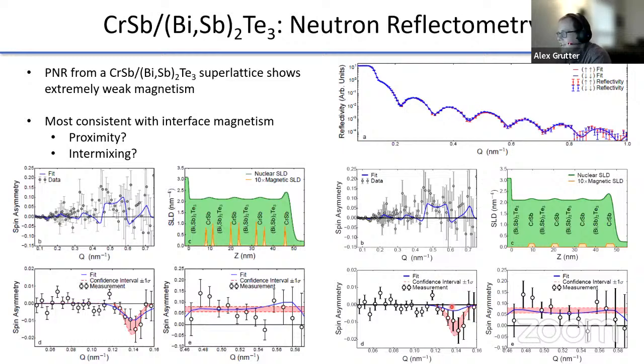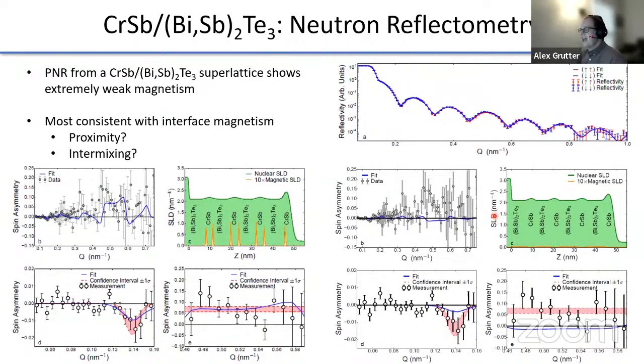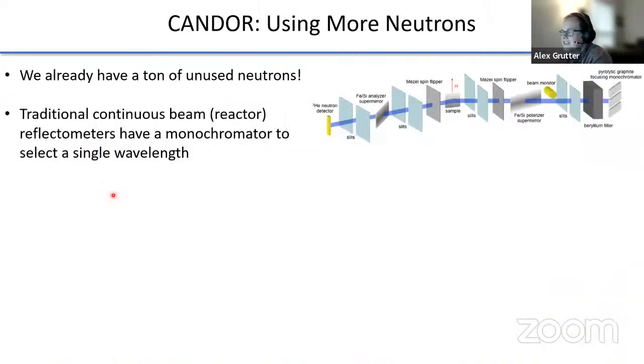It doesn't quite catch it here if it's magnetic chromium antimonide, but it's close. It definitely isn't uniform magnetization in the bismuth antimony telluride. But what this should really tell you is that after 5 days of counting on this, we got a very noisy data set. And so it worked, but barely. And clearly the problem that we often run into is that our error bars in the neutron reflectometry data are just too large. And so how do we deal with that?